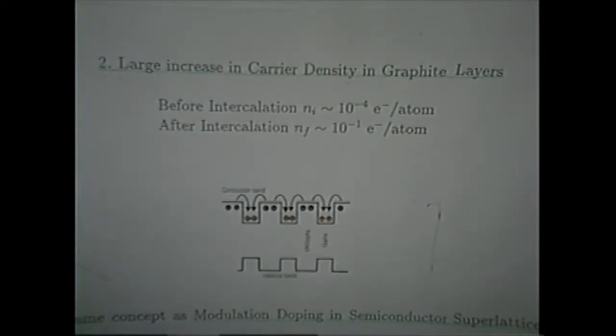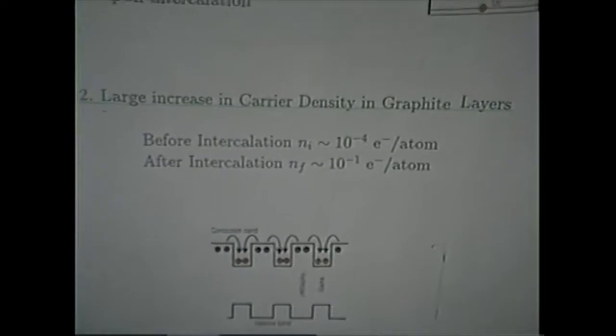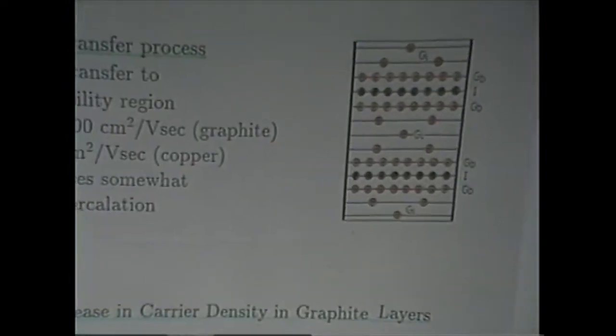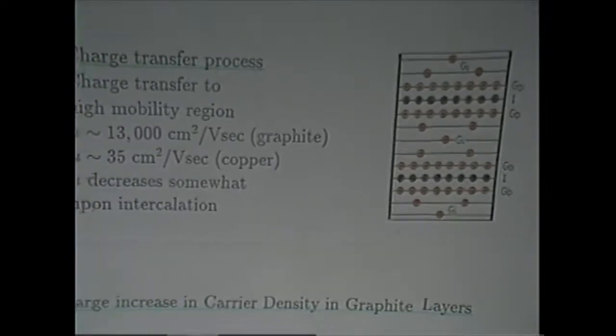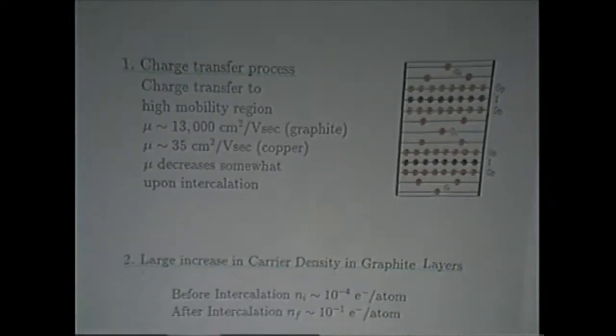Now, the reason why this whole thing works so well is that the carriers are taken from regions where they have low mobility. For example, a metal like copper normally has a very low mobility. 35 centimeters squared per volt second is a small number compared to 13,000, which is characteristic of graphite. So if you can take the carriers from a low mobility region and promote them into a high mobility region, you can really benefit from that high mobility.